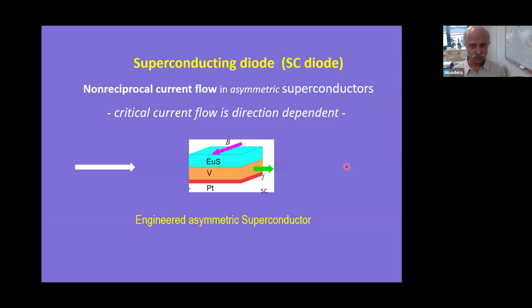Now let's talk about the superconducting diode. Since we had this platform already, except gold is missing here, of course, we can even add a thin layer of gold. It doesn't make so much difference. This is the superconductor. Then you have a ferromagnetic insulator on the top. What we found was that when we send a current through this, we can actually see non-reciprocal behavior. This kind of superconductor we call an asymmetric superconductor because the two interfaces are different. This is a very high spin-orbit material, platinum, which is a heavy element, whereas europium sulfide is a ferromagnetic insulator. That's what theory predicted, that if you have such a system, you should see this non-reciprocal behavior or diode effect.